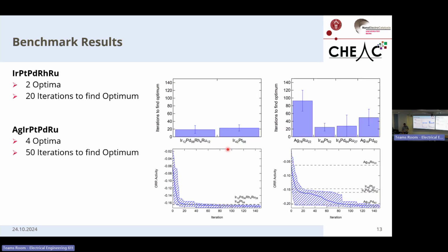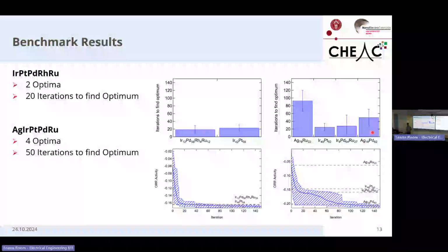In case of the silver, iridium, platinum, palladium, ruthenium space, it takes a bit more iterations to find the global optimum. The reason now has to do with the fact that there are 4 optima present. And sometimes the algorithm finds a local optimum and spends some time trying to improve this local optimum before moving on to a next unexplored region. So here on average, you need 50 experiments. And this 50 experiments became more or less a standard in the field of high entropy alloy catalysis as an average number of experiments you need to do to search for an optimal catalyst in the high entropy alloy space.